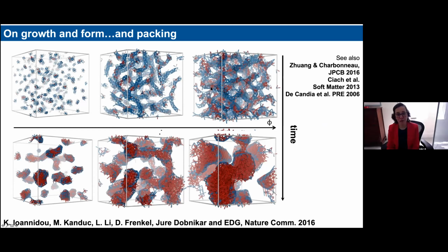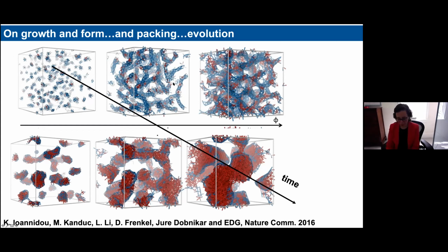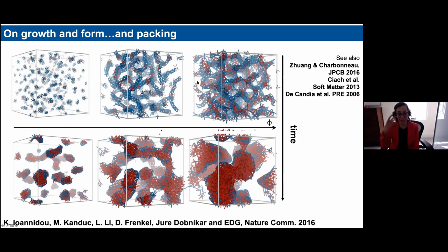And then the fibrils branch to form a gel. So the growth of the fibril now is very fast. In fact, it's a process that we can map into the acceleration of the gel formation that I showed you in the beginning. And then the gelation that occurs in presence of this interaction actually favors very early stages percolation and therefore mechanical properties. So I can start to have a somewhat solid material very early.